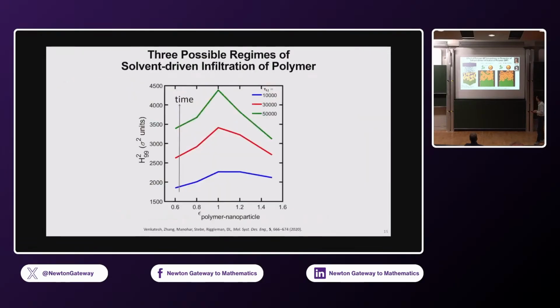Okay. And then what we can do is we can take a look at what the effect of strength of polymer nanoparticle interaction is. So as you go from left to right, stronger interaction. And this shows where the front of that infiltrating polymer species is, the very front, okay, at different time points. So what you see is that when the strength of interaction is fairly weak, there's some rate. But as we strengthen that interaction, it actually goes in faster. But then when you further strengthen that interaction so that they become more stickier, it actually slows down. Okay, so it's not monotonic.